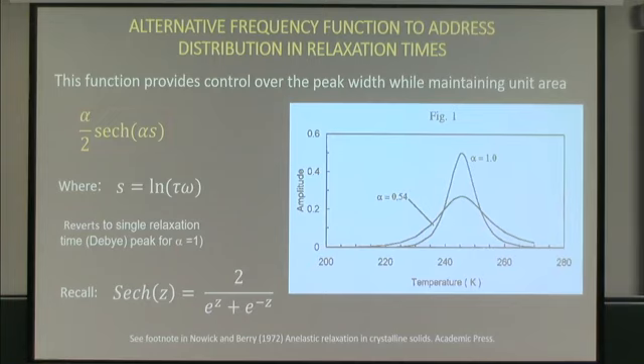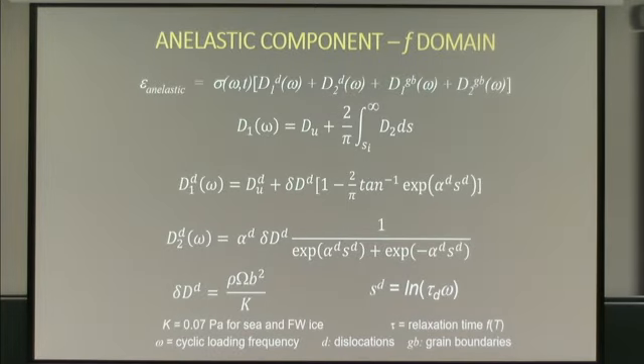The frequency response is called a Debye relaxation curve. It's a single relaxation time that has a very characteristic relaxation curve. It doesn't work for ice. We have a lot of coupled grains, so we have to account for a relaxation time distribution. There's this real clever little function that I'm just going to substitute in for the frequency dependence of this model that occurs in a footnote only in the 1972 edition of Nowick and Berry, Anelastic Relaxation in Crystalline Solids. I've seen it used a couple of places, but it's perfect for ice because we can apply this to both of our relaxation mechanisms. The only restriction on these curves is that they integrate to 1. This function, as a function of this term alpha, lets us broaden that peak out in response to the relaxation time distribution quite handily, and it always integrates to 1. What's not to love? You'll see that repeated through here.